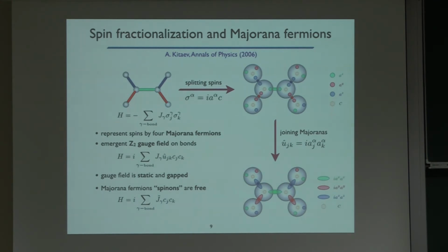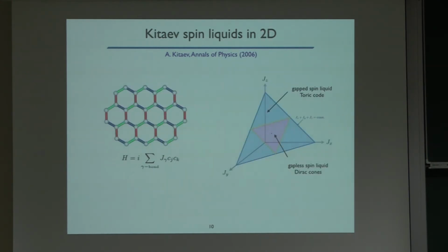Okay. Good. So let's look at what happens if we put this on a honeycomb model. So now we have this free Majorana hopping problem on a honeycomb model. This is the phase diagram that you get. So what do you see here? You see that we have three different coupling constants. We allow them to vary. And we find that there are two different types of phases. So if one of the coupling constants is much larger than the other two, then we're in the blue regions of the phase diagram. And that is a gapped spin liquid.